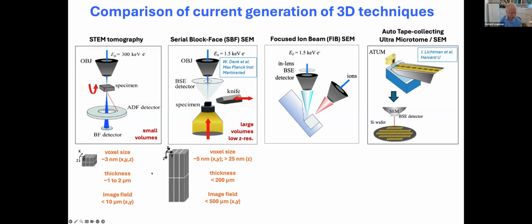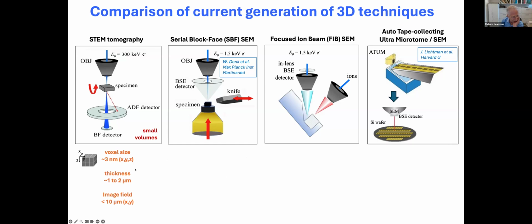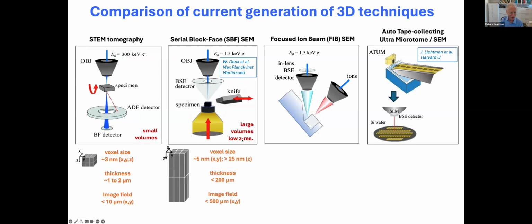And so again, let me say here that in the STEM tomography, you can get small pixel size down to, say, 3 nanometers, but you can only look at thicknesses of about 1 to 2 microns, and image fields of typically 10 microns, so small volumes. In the serial block face, you can get large volumes, and in X and Y, you can get, say, 5 nanometer pixels. But your voxel size in the Z dimension is limited by the section thickness that you can cut off, and 25 nanometers is probably the best you can do, and more typically perhaps 50 nanometers. You can collect quite a lot of data this way, and look at samples that are even up to 0.5 millimeter in size.